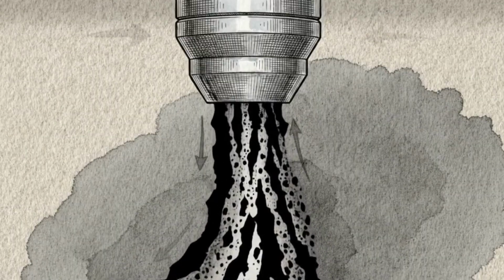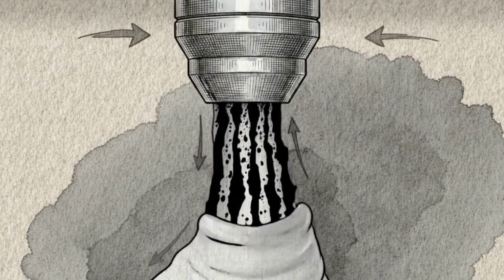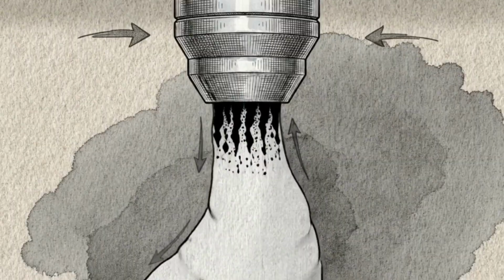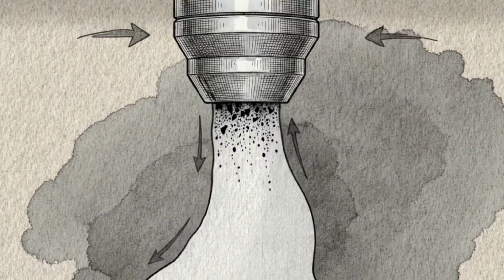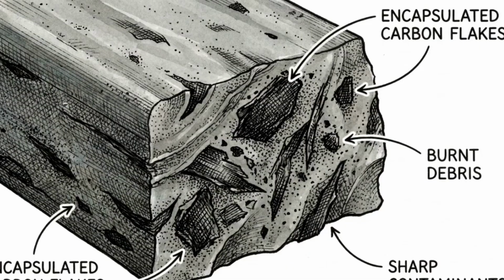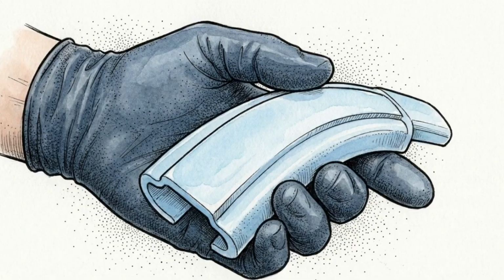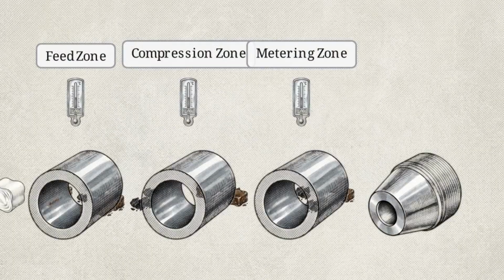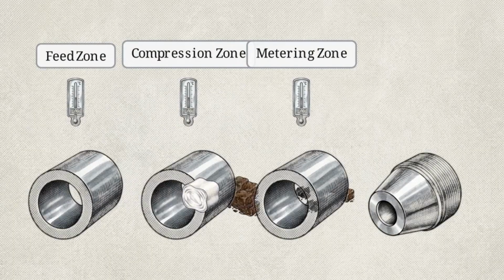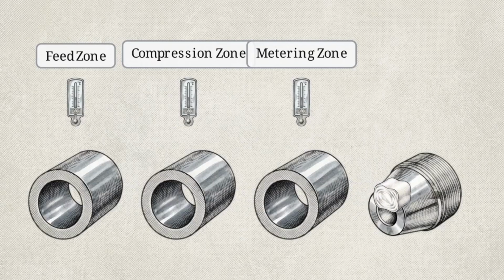Watch the material exiting the nozzle. You are looking for the active transition from the contaminated run to the pure purge compound. Those thick, dark streaks in the stream are the encapsulated carbon deposits and burnt elastomer being physically pulled out of the machine. Once that output stops streaking and holds a uniform color, the contamination has been successfully removed. Maintaining steady forward pressure ensures the degraded residue is fully evicted out the nozzle, rather than just shifting into a different zone inside the barrel.